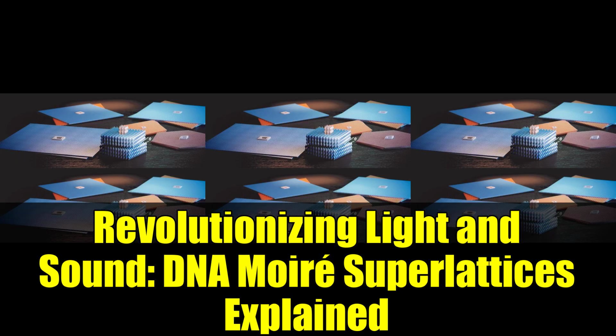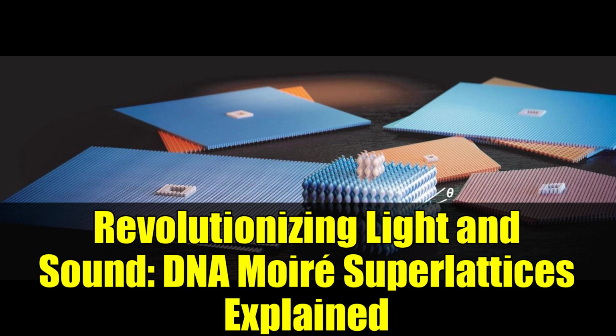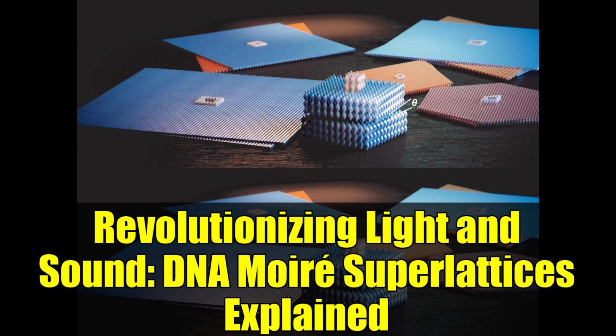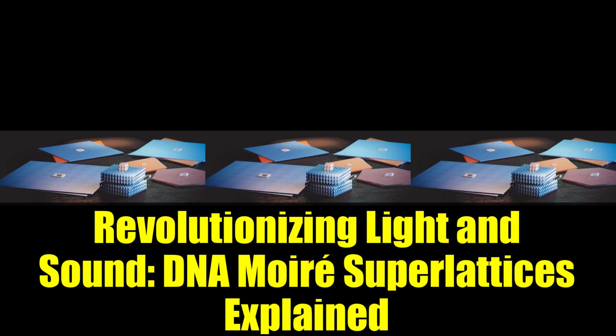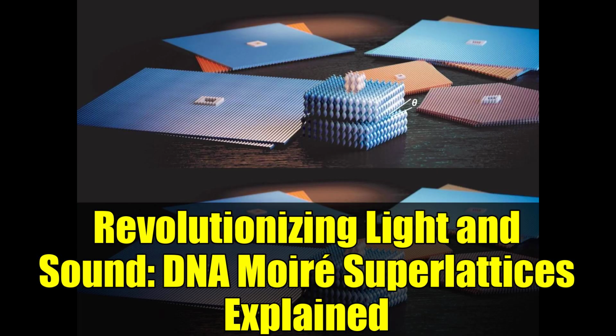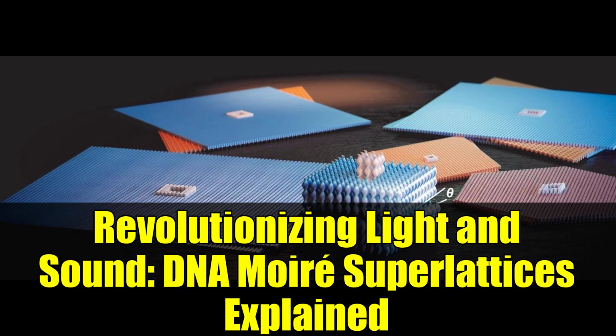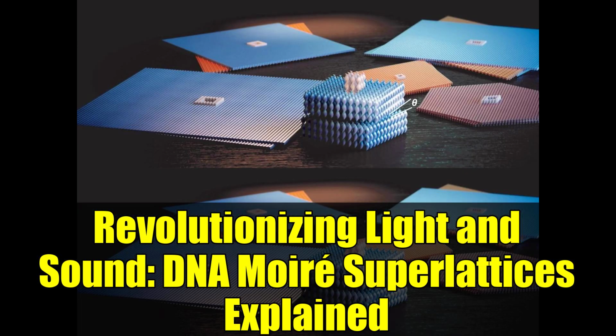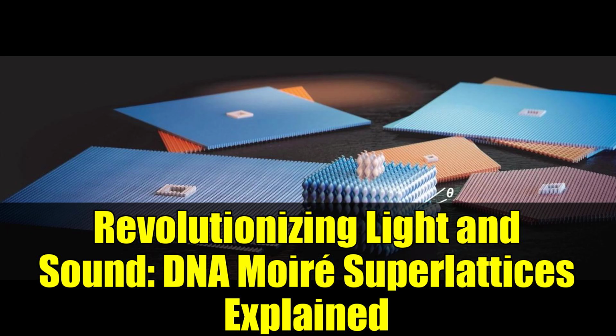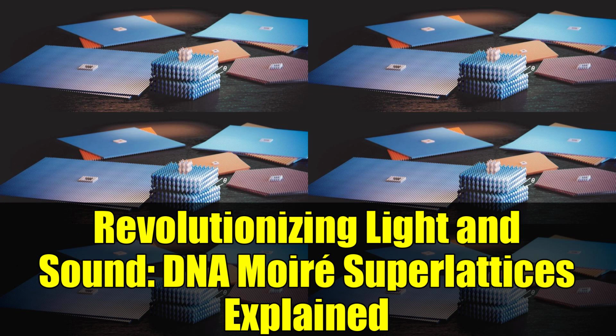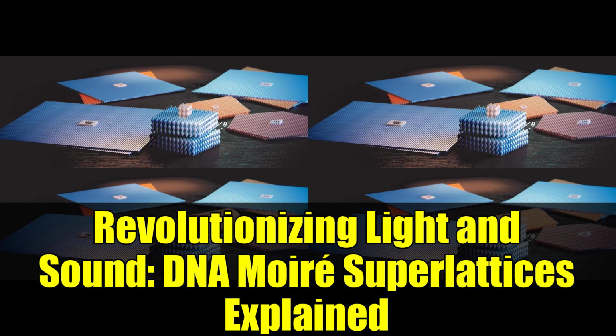The Stuttgart team has centered their methodology around this principle. "We encode the geometric characteristics of the superlattice, such as rotation angle, sublattice spacing, and lattice symmetry directly into the molecular design of the initial structure, referred to as the nucleation seed. We then allow the entire architecture to self-assemble with nanometer accuracy." This nucleation seed serves as a molecular instruction manual, directing the growth of two-dimensional DNA lattices into precisely twisted bilayers or trilayers.